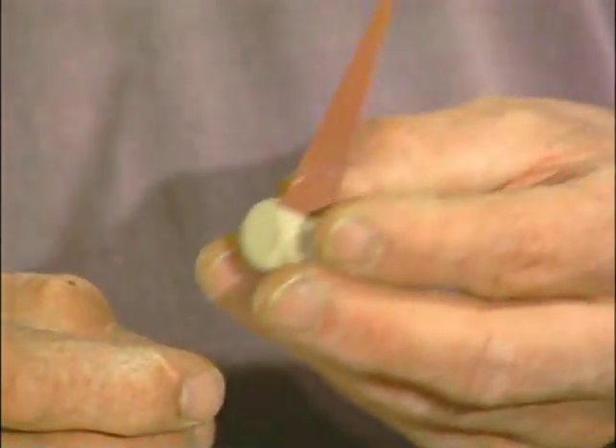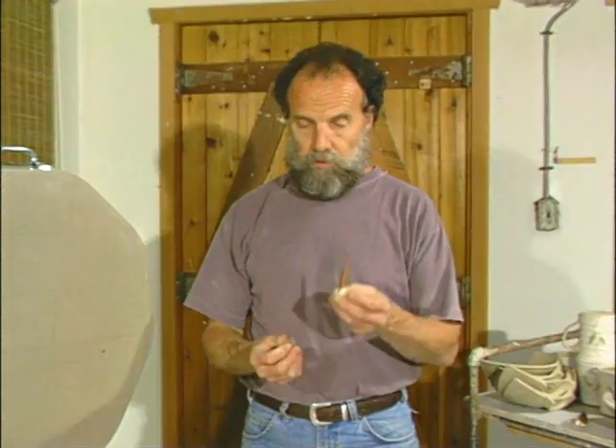Cones come in 2 sizes. This is a large one. We'll set that inside the kiln where we can see it through the peephole as the firing progresses. What occurs is that as the temperature increases, the cone melts, and in this particular case, for the small cone, the melting of the cone triggers the release of the kiln sitter.